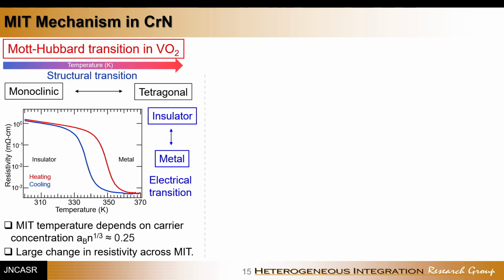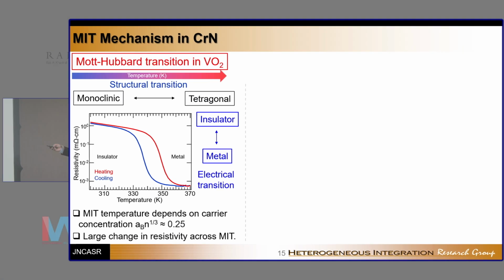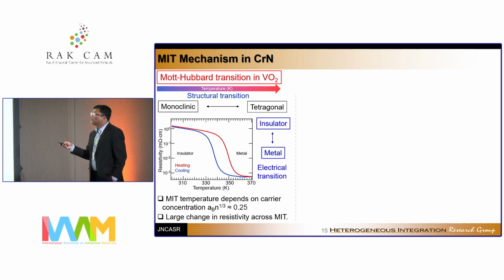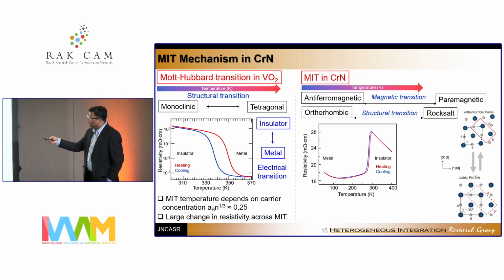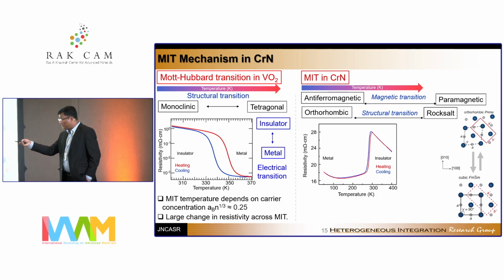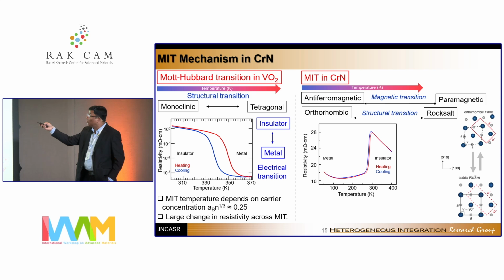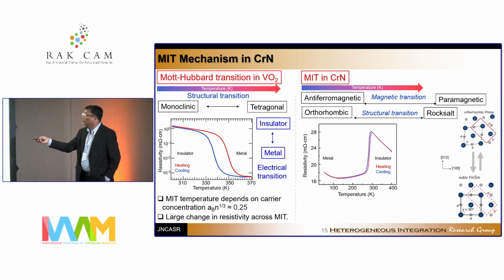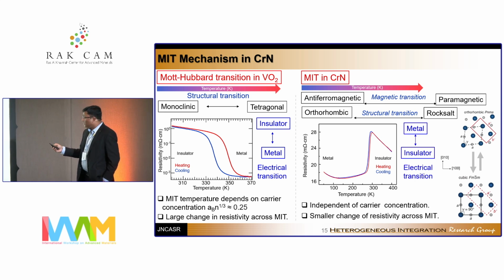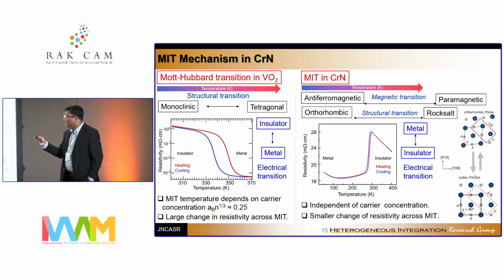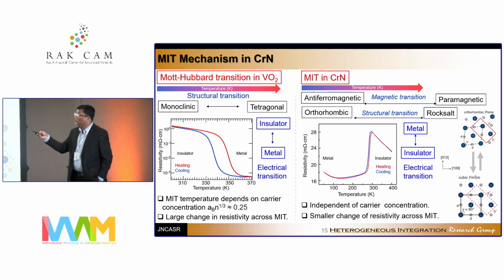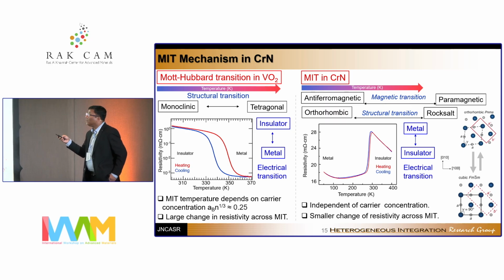So now if I compare the metal insulator transition in chromium nitride with VO2: VO2 shows this insulating low temperature phase to high temperature metallic phase, with 10 to the power 3 orders of magnitude change in resistivity, and a monoclinic to tetragonal structural transition. But compared to that, chromium nitride shows the opposite behavior. The resistivity at low temperature is actually low, so it undergoes a metallic to insulating transition as you go from low temperature to high temperature. So obviously the physics which really explained the transition mechanism in VO2 won't explain the transition mechanism in chromium nitride.